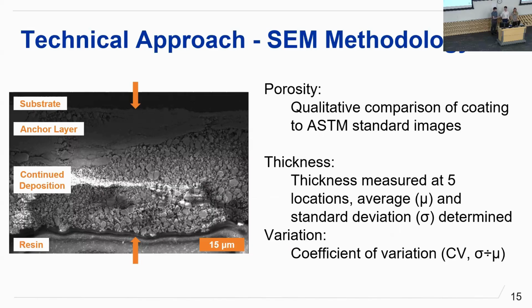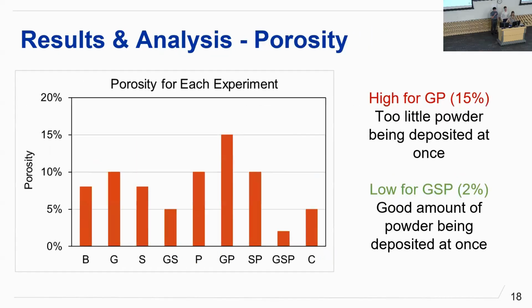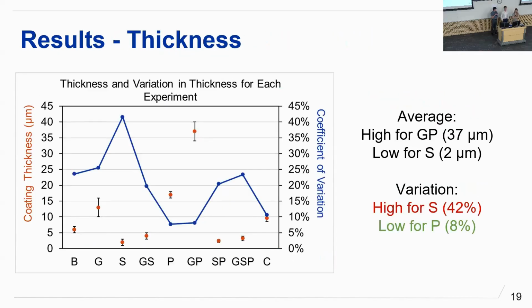Quick question. Were all your coatings the same thickness? No, our coatings did have a variation in thickness throughout. That's just due to the different amount of passes we had, which resulted in different thickness between the different samples. Do you think it would be worthwhile to normalize some of your results based on coating thickness? I think that would be something great to look into. That definitely could give us some more accurate data for selecting the best overall coating, but that was just something that we didn't end up looking at, but that is a great idea because we didn't consider that.